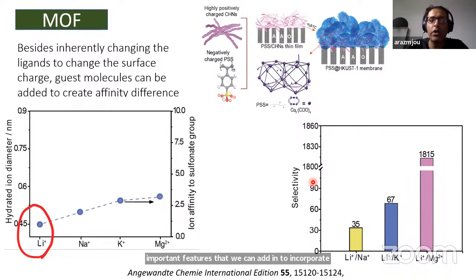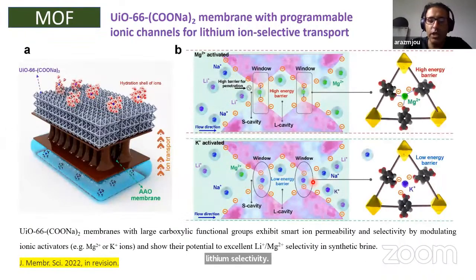What we found is that the ion affinity to sulfonated functional group is very important. Using that ion affinity, you can introduce linear polystyrene polymers with abundant sulfonated groups, and we can make a membrane which shows a high lithium selectivity. We also found that by creating energy barriers within the MOF nanochannels, we can create a sort of energy baffles within the nanochannels, which alters the movement of ions, and that provides us selectivity between lithium and sodium.